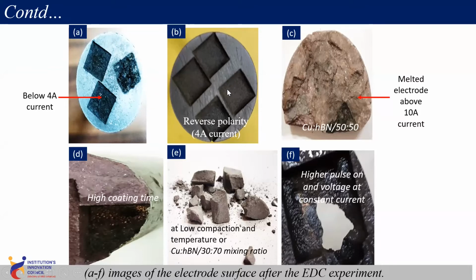So this is a reverse polarity that we are using. By using a reverse polarity, it means the tool is connected to negative, as I have told you in the first slide. So that negative polarity allows a large amount of deformation of the tool from the tool surface. So this is a copper HBN ratio. Above 10 ampere current, the tool gets melted.